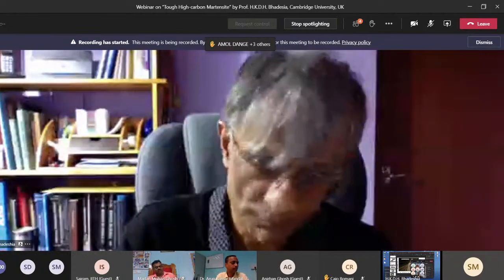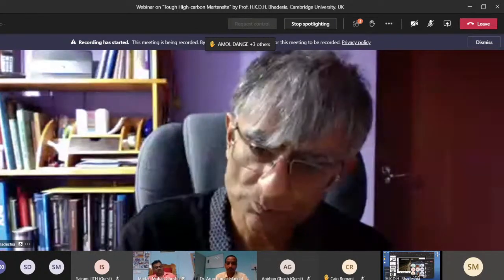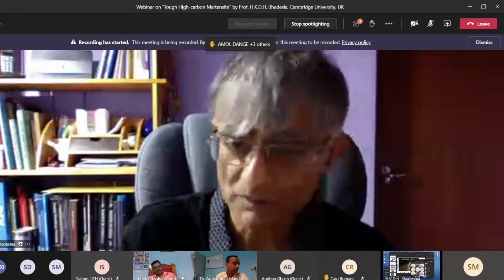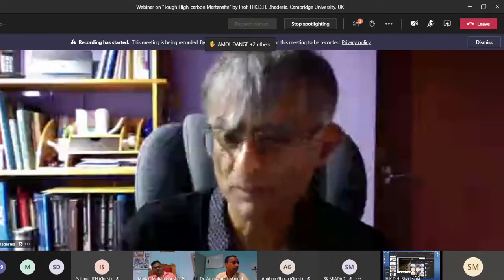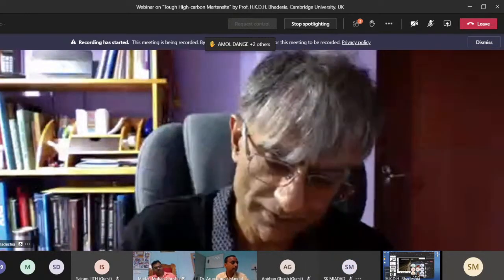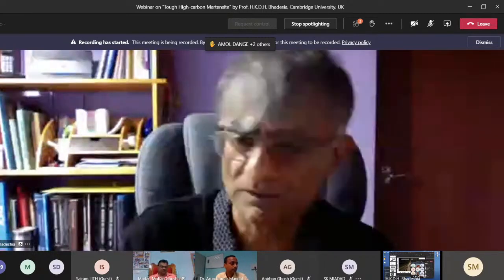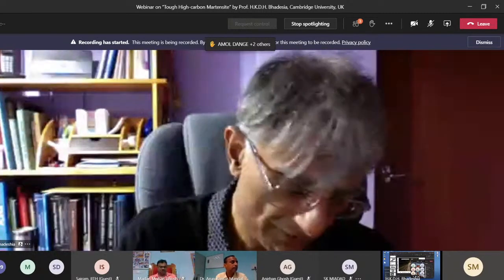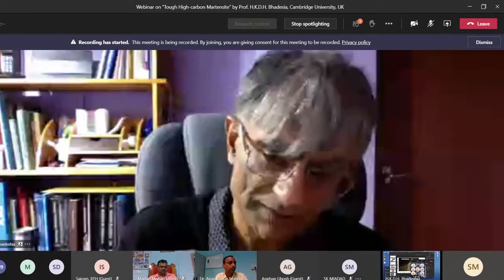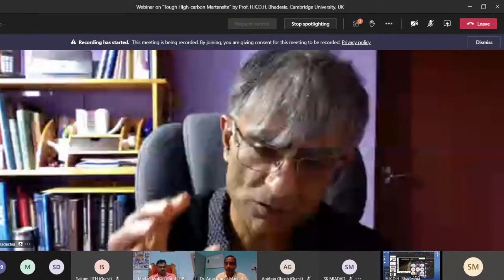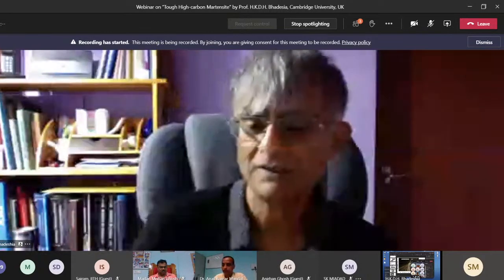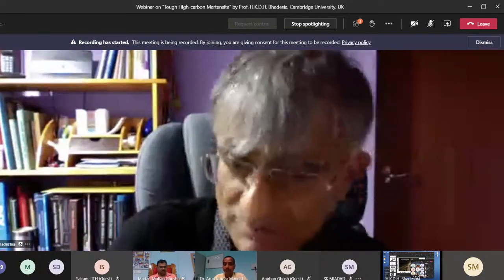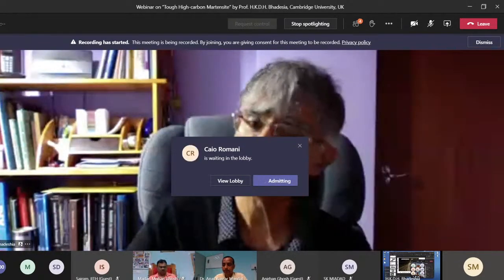Arc welding works perfectly okay, and there are two things you can do. One is to use a consumable, and it's very easy to make a consumable composition by altering the coating or the core of the wire, and that has been done. But ideally, we would like autogenous welding. That means you're not actually using a filler, because then you would have the same material just being joined together. And that has also been tried successfully.